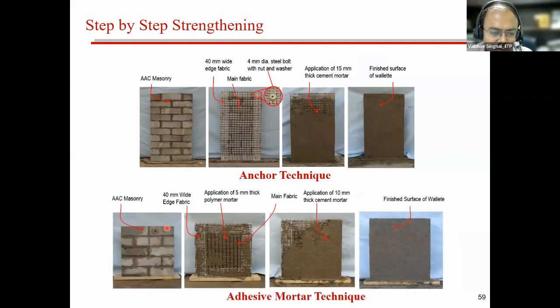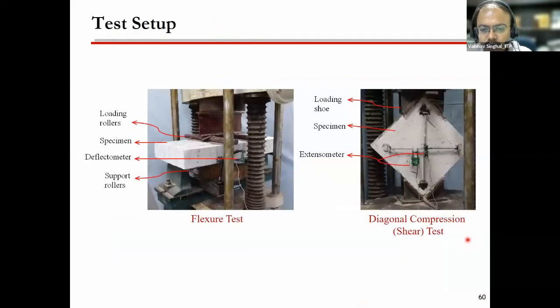Whereas in the other technique, this is your masonry surface, then we applied the fabric. We kept the edge fabric also, just to have similarity with the anchor technique, and then applied the polymer mortar, the adhesive mortar, so that the fabric should properly adhere to the surface. And then after drying, we applied the 10 mm thick cement mortar. So these were the two techniques.